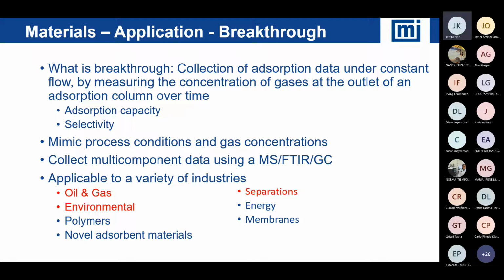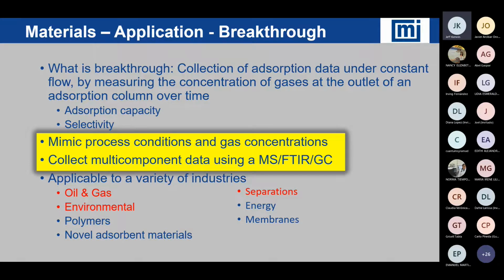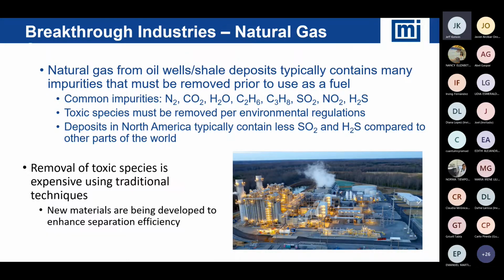And the benefit now of breakthrough, and the reason we are so interested in breakthrough, is we want to be able to use multi-components for the gas feed. So having CO2 adsorption or hydrogen or oxygen or argon is very nice for understanding texture. But when we get to the application space, we want to know how do these materials truly perform? What's the impact of water on my application, on my material, and the performance, and where we go with research? Can we do things that are very similar to the process conditions that we're actually going to encounter? That's one of the benefits of using breakthrough. We see it extensively.